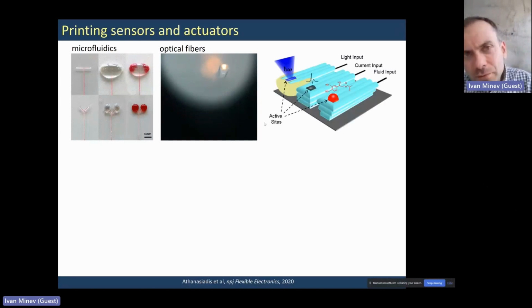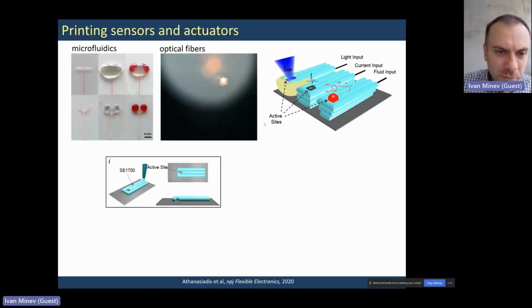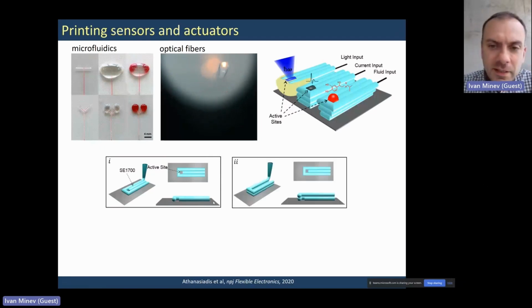But we soon found that this was probably not the most optimal way to make the fibers and the individual components. So we switched to a more classical, layer by layer way of doing things. Without going too much into the details, a typical way to make an electrode would be to start with printing one layer of material where a little area is left unexposed. This is going to be the active site of our device, and then continue with building further layers.